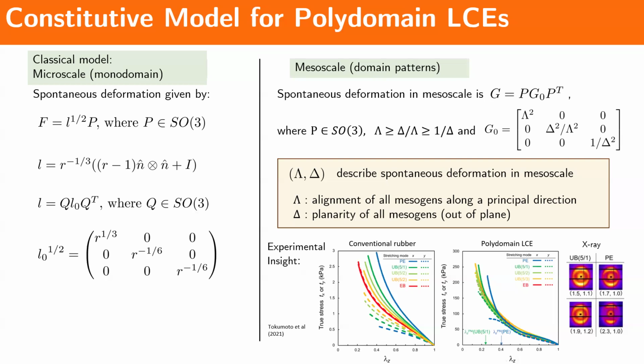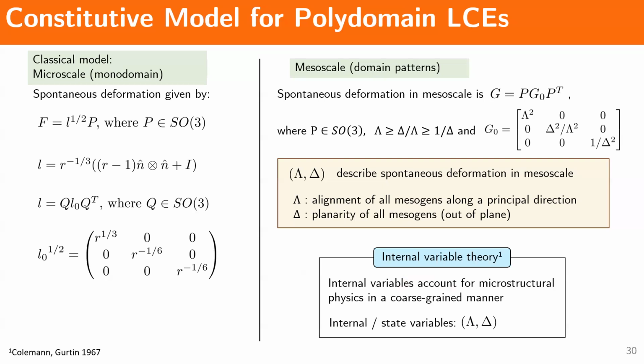are going to be enough to capture the macroscopic quantity of interest, which is our macroscopic stress. So now we borrow concepts from internal variable theory and say that lambda and delta, which are linked to our spontaneous deformation in the mesoscale, are our two internal variables. The internal variables account for the microstructure formation and evolution in a coarse-grained manner to predict our macroscopic stress. That's basically the whole idea. If we know the state of our internal variables at that particular space and time, we know enough information about the history and the microstructure of these materials to predict the stress.